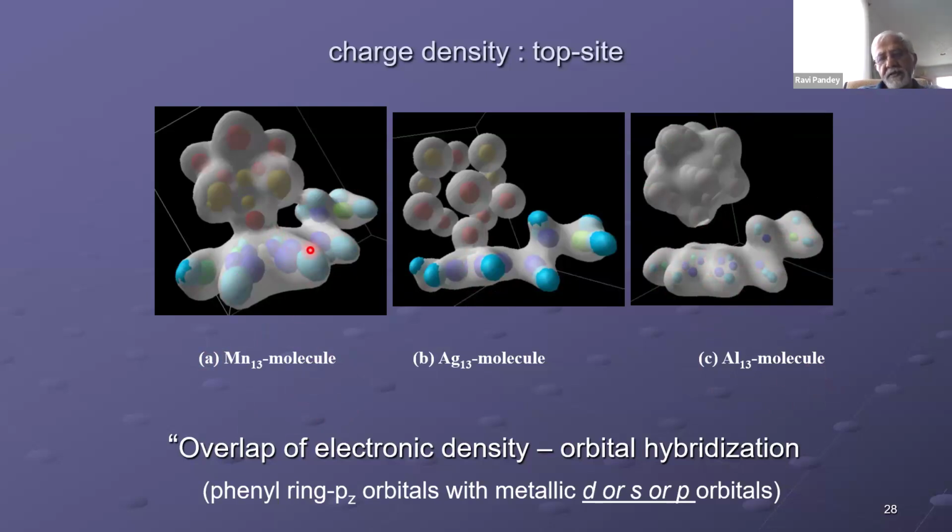So the forming of a bioconjugated complex comes down simply to overlap of electron density, and what we have is orbital hybridization. Coming from physics, I talked to my chemist friend, Dr. Karna. He saw these results and said, wow, it does make sense. The reason is that dopamine has carbon rings, with a pz electron forming a pi electron cloud. This pi electron cloud interacts through pd interactions very, very strongly compared to ps or pp hybridization.